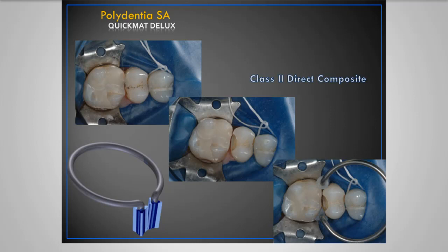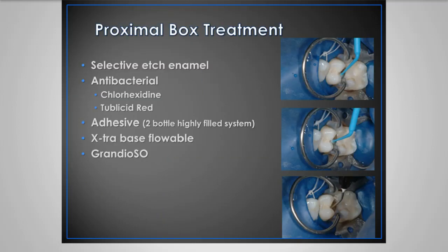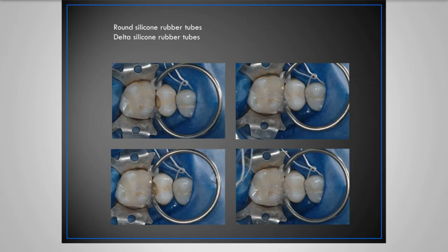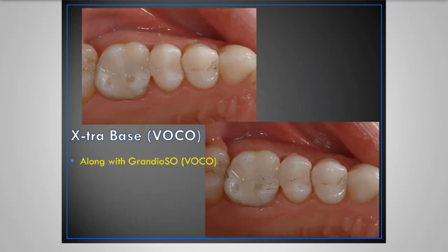And so in this case, we're going to go in and place this Polydentia SA Quick Mat ring system, which is really nice, and get good adaptation of that ring system, place our bonding agent, followed by our Extra Base flowable as our first increment, and that's a 4mm replacement. And after placing that to get good adaptation, we'll cure that in place, followed by the Grandio SO as my enamel replacement. And so you'll notice here we're placing the different increments in, followed by curing, and we get a great looking final product.